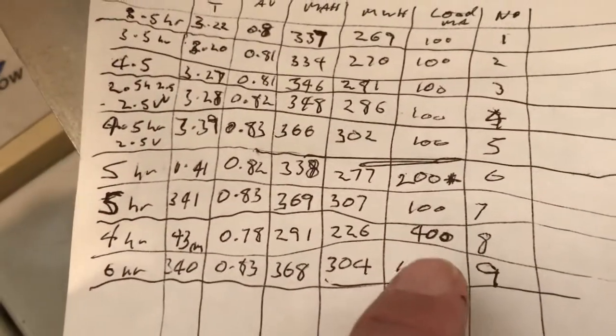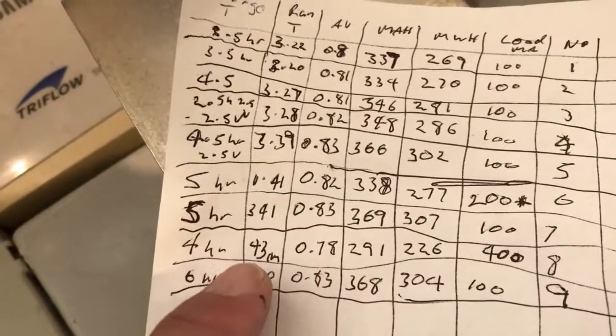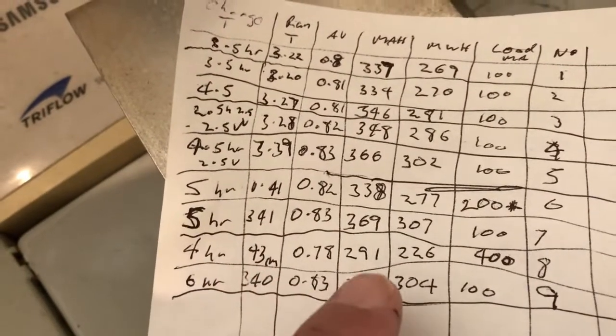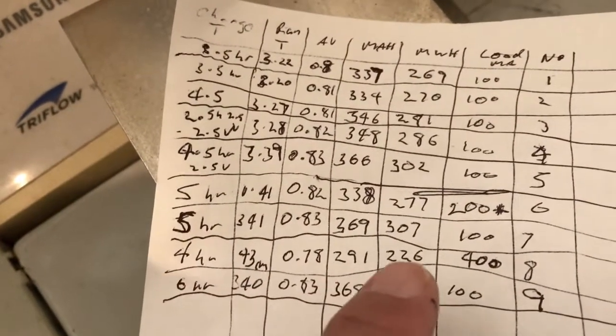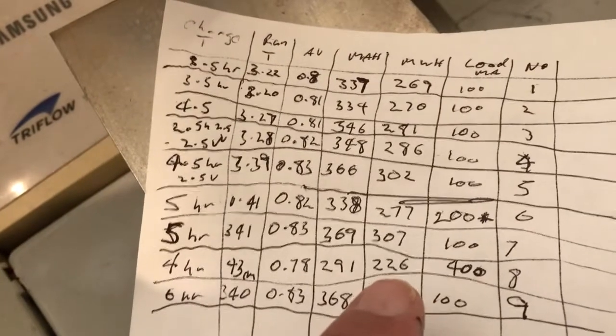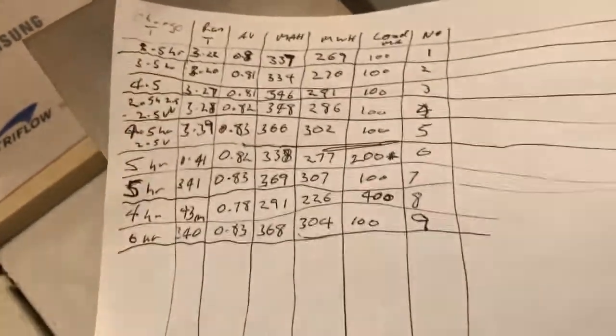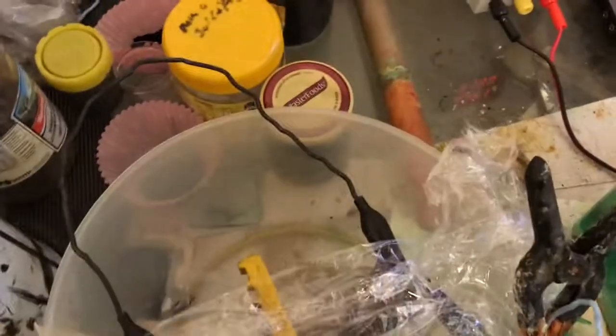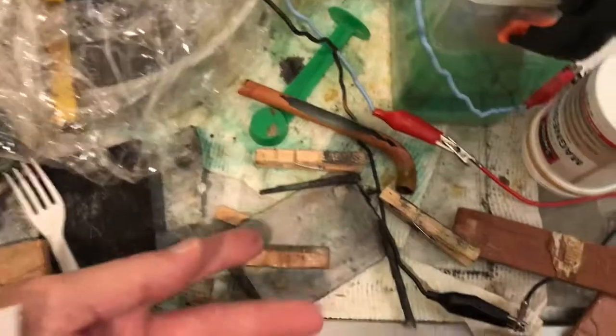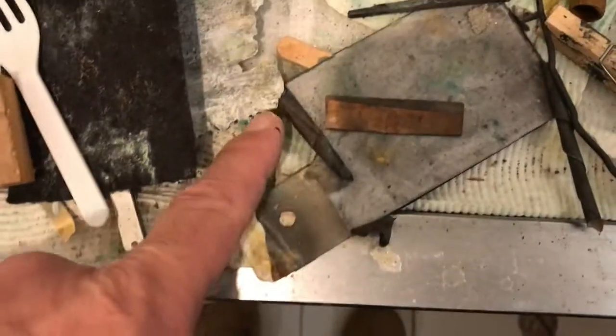I did a 400 milliamp run here. We only went for 43 minutes though, but we did get 291 milliamp hours and 226 milliwatt hours from a 400 milliamp run, which ain't too bad for the cell. There's no degrading yet, but that left side cell at the bottom is broken. It was all puffed up before I started. I thought it would hold because it didn't tear like this one, but it's starting to tear at the bottom,